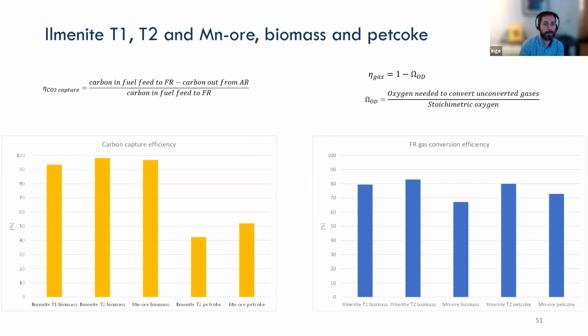Yeah, here we see the same figures. Only here are the 3 oxygen carriers included, and for biomass and petcoke. Yeah, the carbon capture efficiency was high for all oxygen carriers when using biomass as fuel. When using petcoke, it was low with ilmenite, but it seemed like the manganese ore was a bit better. Yeah, the gas conversion efficiency, we saw that the manganese ore did not perform as well as the ilmenites, both for biomass and for the petcoke. More pronounced with the biomass.